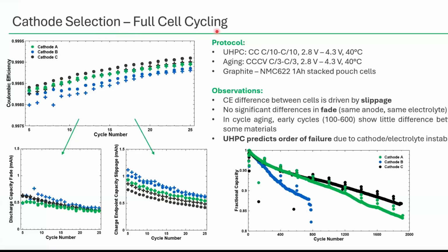Moving these into full cells, this starts to get a little more complicated. We're not directly just measuring the cathode. We're looking at fade happening, lithium inventory loss into the anode. What's really interesting is we look at these different metrics, the Coulombic efficiency, and we see that cathode B, which had the highest parasitic current, is the lowest Coulombic efficiency, then cathode A, then cathode C. So this follows that direct parasitic current measurement very well.